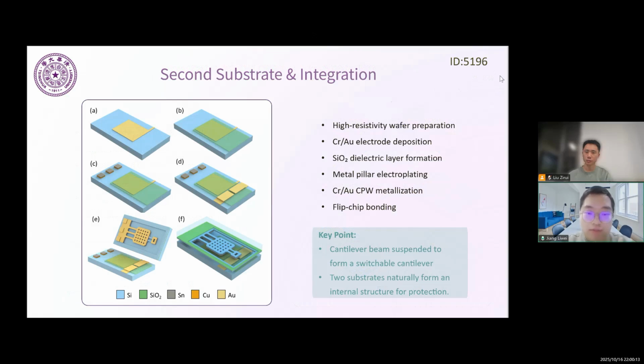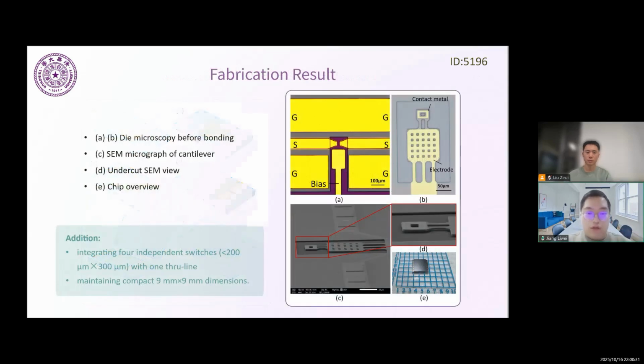What's great about the process is that we don't need through silicon vias, no bulk thinning, and no exposure to particles, which keeps the device clean and robust. Here are some images of the fabricated device. Under the microscope, we can see excellent alignment between the cantilever and the CPW before bonding. From the SEM images, we confirm a clean undercut with no residual oxide, which is critical for proper release. The final chip is 9 mm by 9 mm, and it includes 4 independent switches, plus a through line for calibration.